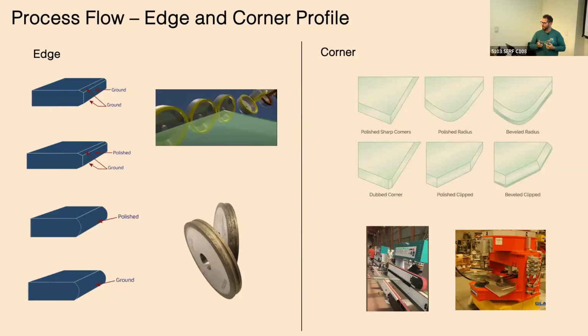And there's the pencil edge, you'll hear bullnose, but basically it's a big rounded edge. It's the strongest edge, if you will, because you're not putting that glass in tension and you're not having any sharp corners. Things you have to watch out for are, when you're grinding, the grinding wheel is also wearing away at the same time. Depending on how well your glass is attuned to the grinding wheel, if it's up high or down low, you can get chips on that surface right at the transition from the flat to the edge. You tend to get radial chips there. So little teeny, like a scratch that John showed, similar to that, you'll see little digs that look like a little rabbit kind of ate your side on a microscope.